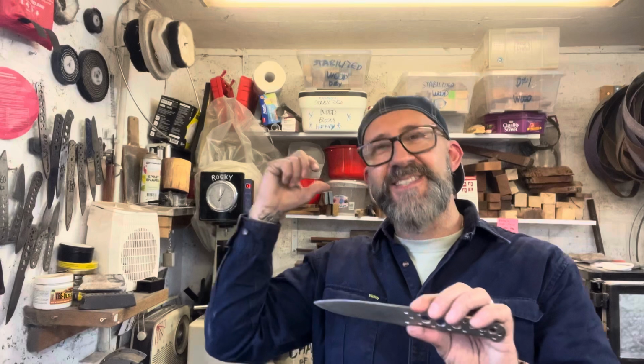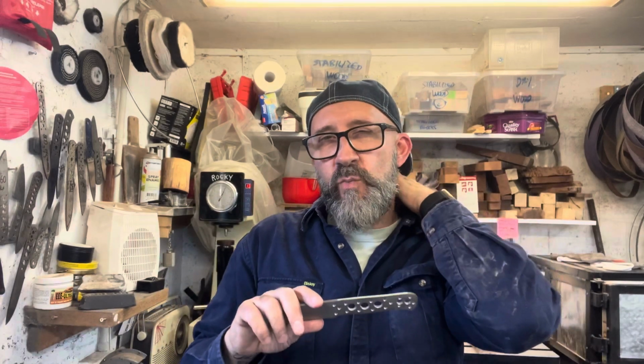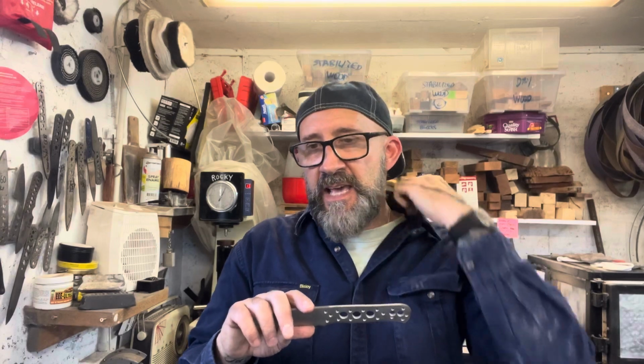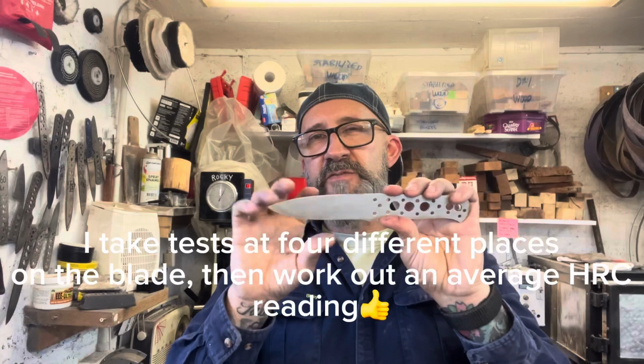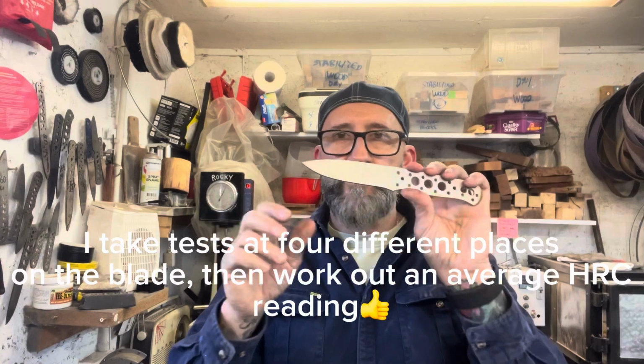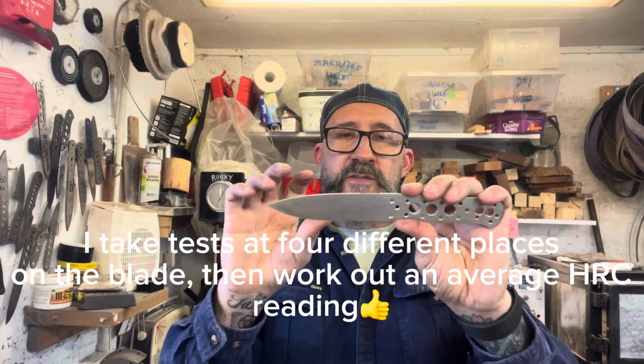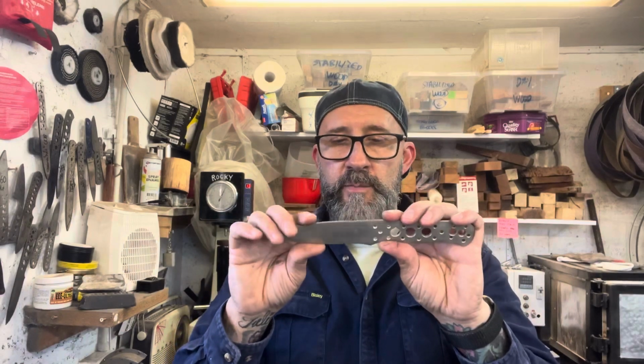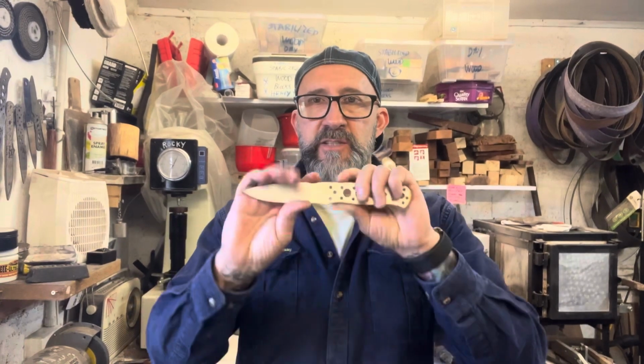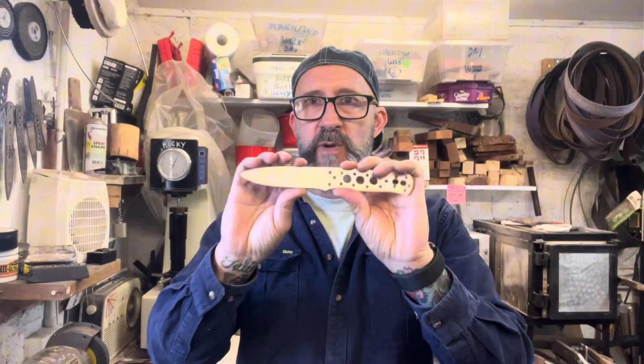Took it out, let it cool down, tested it on the hardness tester, and we were around about 61.5 HRC. So I put it back into the tempering oven for another 2 hours at 170, and then it's finally come out, and we're around about 60, 59.5, 60 overall hardness. Which is perfect for an AEBL blade. So there we go, really happy with that. 60 HRC, absolutely spot on for AEBL.